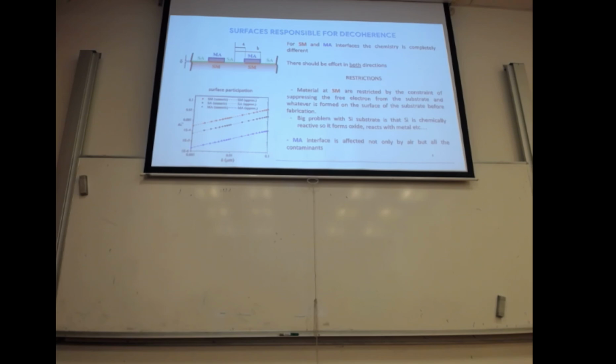Then what you see is that depending on the thickness of this interface, the participation ratio is different. For example, if you consider the metal layer, for a small thickness it has the least participation ratio. The substrate is like this. And the majority of the participation ratio is in this interface, that is the substrate-metal interface.